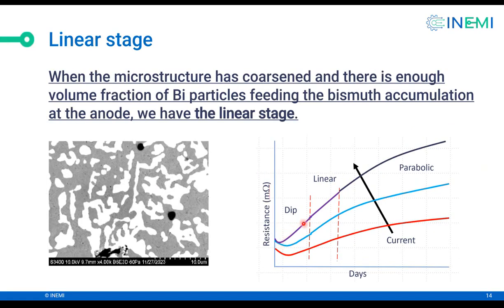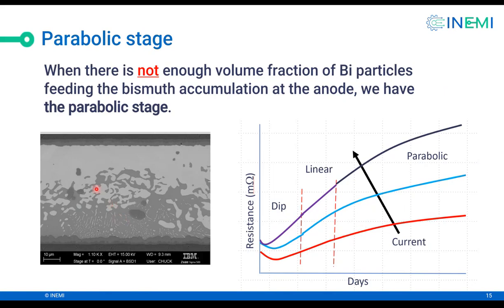And then the increase happens because the bismuth starts collecting at the anode and becomes thicker and thicker. That gives us a linear region. Then we get to the stage when the bismuth gets very thick on the anode, but there's not enough bismuth left to feed this region. So the thickness cannot increase; the thickness increase becomes slow. That's when the resistance plateaus. We get the parabolic region. So that explains the shape of the curve.